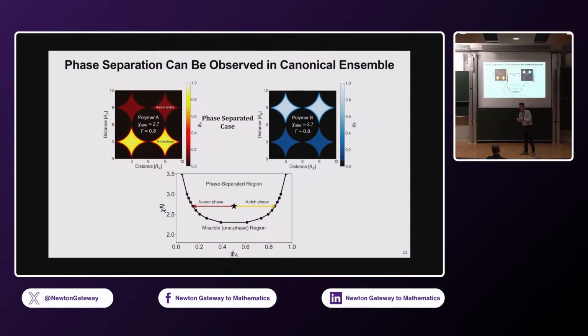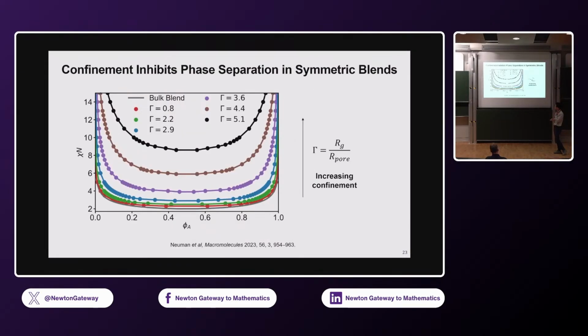Okay? So we basically run these simulations now in a way that the polymer gets very, very confined within these pores. And here is the result. There's a lot going on here, but in summary, as you confine these two polymers in these pores, and the surface of the pore is neutrally interacting with the two polymers, what you see is that the miscibility window increases dramatically. So the phase boundary moves upward in chi N. This is interesting, but why is this happening?